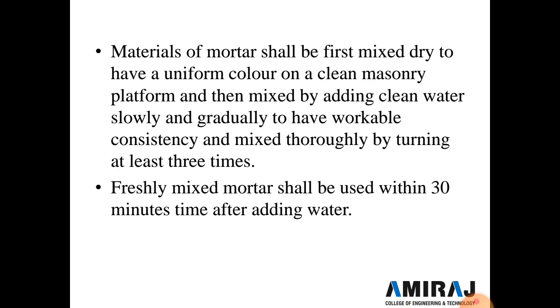Material of the mortar shall first be mixed dry to uniform color on a clean masonry platform, and then mixed by adding clean water slowly and gradually to have a workable consistency, and mixed thoroughly by turning at least 3 times. Freshly mixed mortar shall be used within 30 minutes after adding the water.